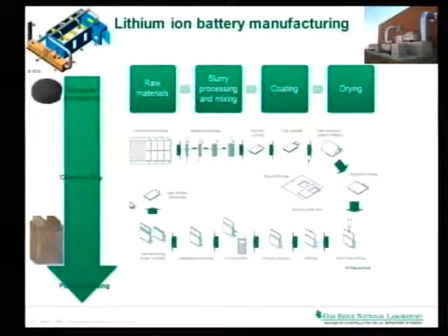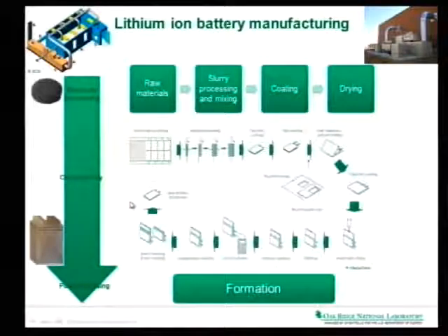All of a sudden, you are having seals which need to keep water out for 10 years under all kinds of scenarios. In a consumer electronic device, that's less of an issue. It sits much less in the rain. It sits much less at very abusive conditions, and it doesn't last that long. So after that, you go through the formation cycling, where you do passivation of surfaces inside your device. You're forming the final electrodes. You're forming the right phases you need to have to get actually a good performance over a long period of time.